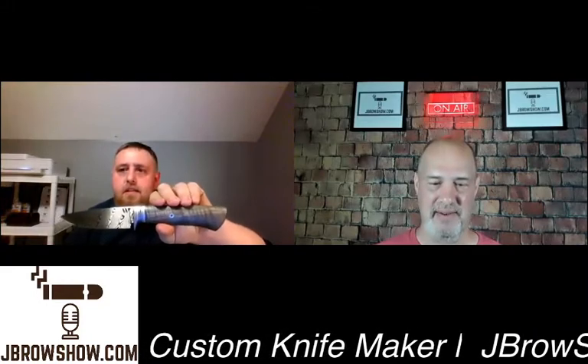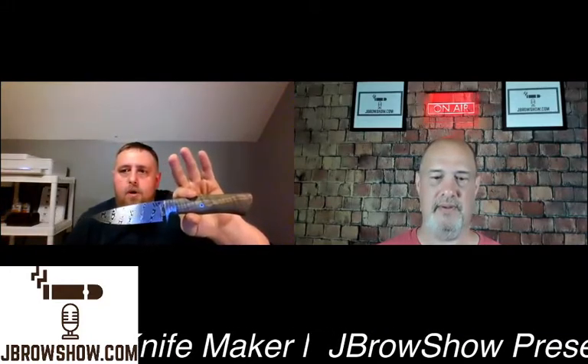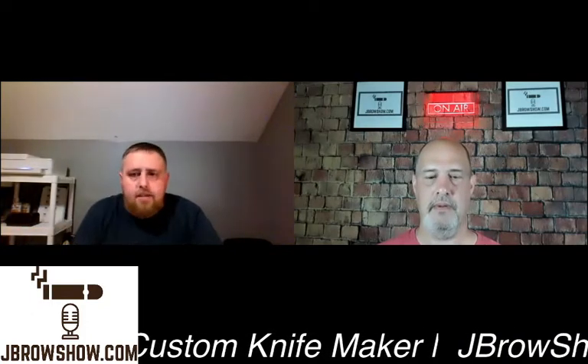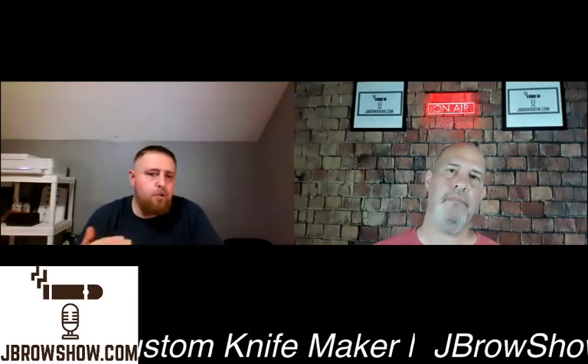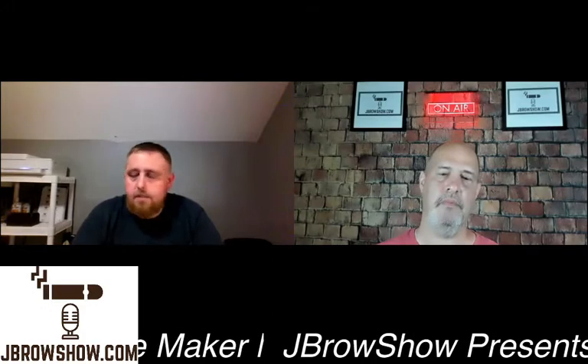But I do have one that's Damascus steel. Look at that. This is one of my woodsman knives, and this is a twisted Damascus. The colors that you're seeing in the steel, the black and the steel tone, are two different kinds of steel. One steel darkens when etched in acid, and one doesn't. You start with an initial stack where you alternate the kinds of steel and forge weld it, and you can draw that out and repeat the process until you get up to the layer count that you're happy with. The higher you go in layers, the finer the pattern becomes.